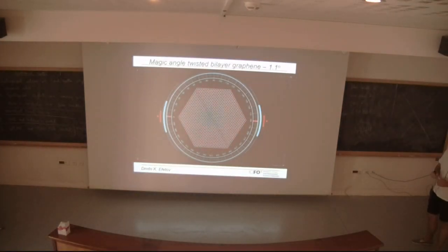Okay, and this was a recent news report. This is just to demonstrate how much 1.1 degrees is, how much you have to twist, just to give you a feeling for what a subtle effect this is. When we fabricate devices, this is by how much we have to twist the top layer with respect to the other to really get this effect. And if we're off by just 0.1 degrees, we can throw away the device. We have achieved nothing. It's done with Scotch tape and PDMS, etc. It's doable, but of course it still needs skilled hands.